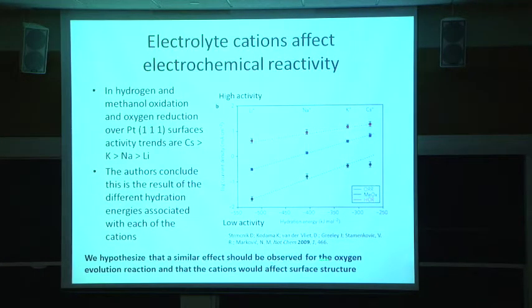We thought there might be a similar effect that we could observe in the oxygen evolution reaction, and that cations would affect the surface structure. Now this is certainly not the only example where the electrolyte plays a crucial role. Here at MIT there's some work on nickel and cobalt phosphates and borates that have electrocatalyst materials that form under the reaction conditions and depend on the electrolyte. Those are all anions. Here we have an interesting effect that could be due to the cations.